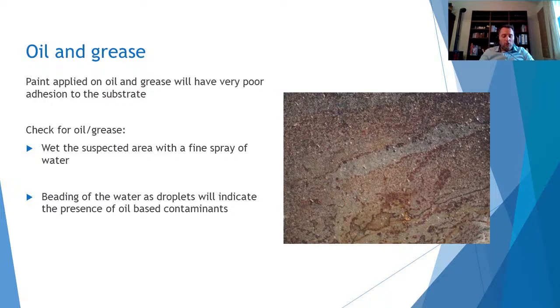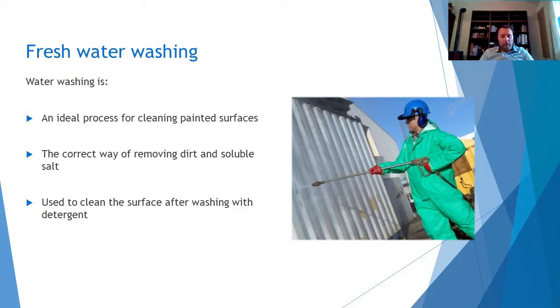Fresh water is a common, if not powerful, solvent and may effectively clean a surface. Water washing is an ideal process for cleaning painted surfaces and the correct way of removing dirt and soluble salt. It is used to clean the surface after the wash with detergent. Also, it is important to thoroughly rinse the surface, particularly when alkaline or acidic materials are used as cleaning preparation. This minimizes the amount of soils remaining and removes residual cleaning material that could adversely impact coating performance.